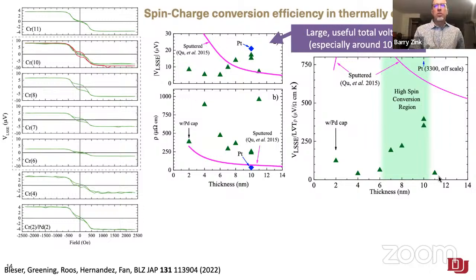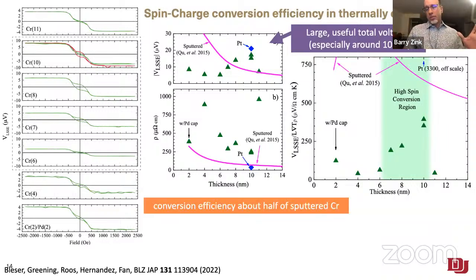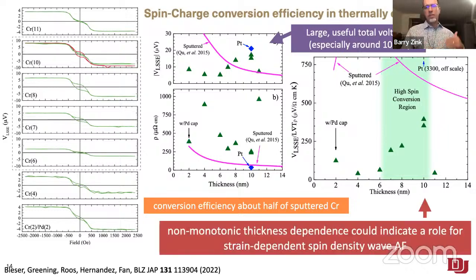So this looked very strange to us until we started asking around from other friends who've been working on chromium for longer, and looking back into the dim mists of the 90s when people understood maybe more about very thin chromium films because of giant magnetoresistance and all this sort of lovely stuff. And you realize that there's lots of phenomena in chromium thin films where you see these non-monotonic behaviors with thickness. The explanation is that as the thickness changes, it also changes the strain in the film. And the strain, it turns out, changes the nature of the spin density wave antiferromagnetism in the chromium.